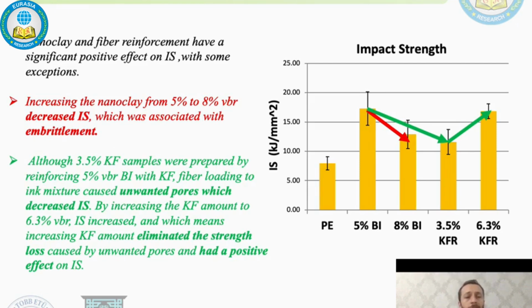The other important result is about Kevlar fiber loading. The 3.5% Kevlar fiber group had a lower impact strength than the 5% base ink group. Since the 3.5% Kevlar ink was prepared by reinforcing the 5% base ink with Kevlar fibers, the expected situation here was that the Kevlar containing group would have higher values than the 5% base ink group, but it didn't happen as expected. It's thought that this situation is caused by unwanted pores formed by fiber loading into the ink mixture.